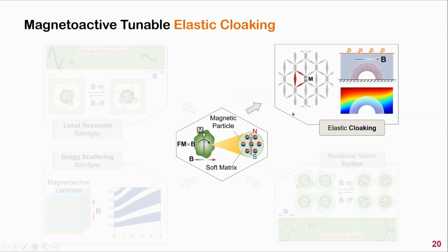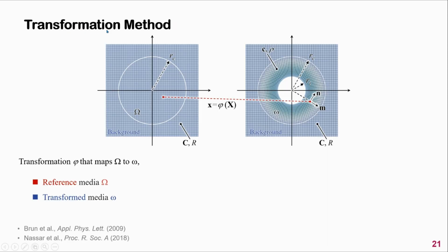Okay, next let's see how to achieve elastic cloaking using magnetomechanical coupling of hard magnetic materials. This is the so-called transformation method that enables cloaking, which means an object is completely invisible from its surrounding. To achieve such a cloaking, the core idea is to design the cloak material, which is also called transformed media. This can be achieved by applying a geometric transformation that enlarges a point in the background and maps it onto the cloak inner boundary. Through this process, the material parameters in the cloak media will be revealed by the transformed